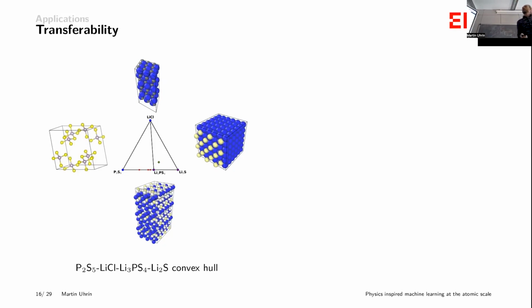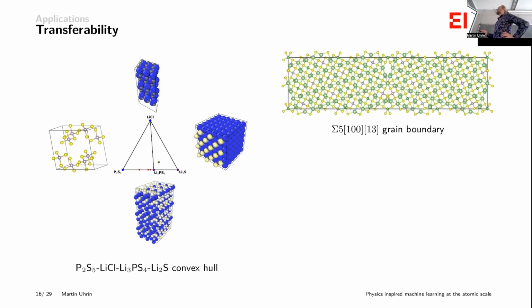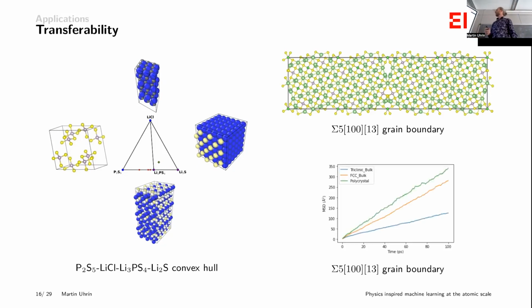So I was already happy with that. And then I thought, okay, great, then I'm fairly confident in going to the next step, which is to at least look at a grain boundary. So we take our crystal, make it bigger, cut it in half, put it together, in this case for this grain boundary configuration, and then run the simulations again to look at the conductivities.